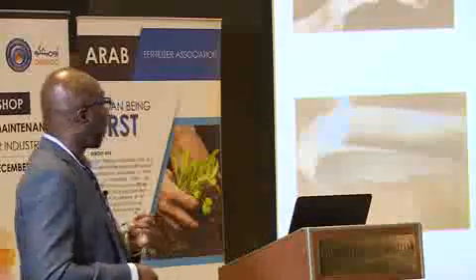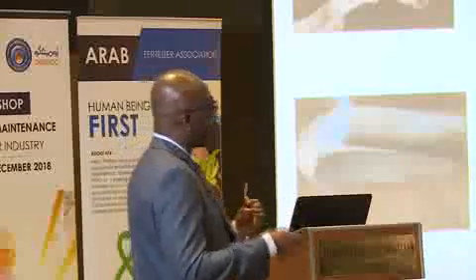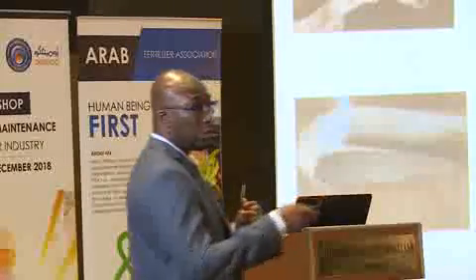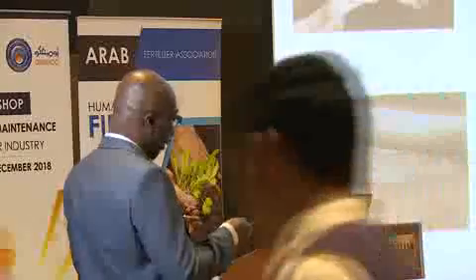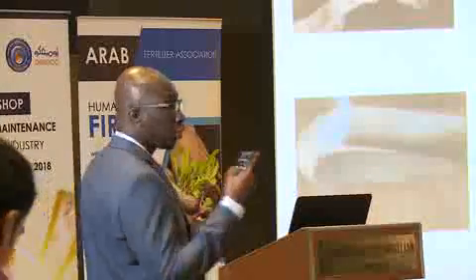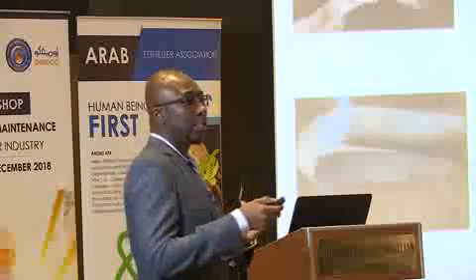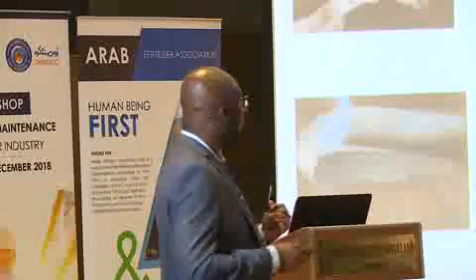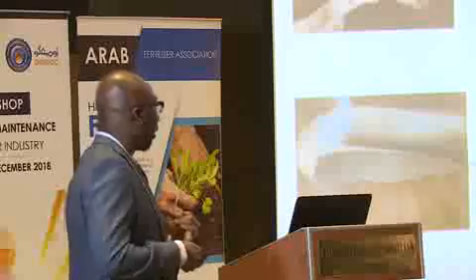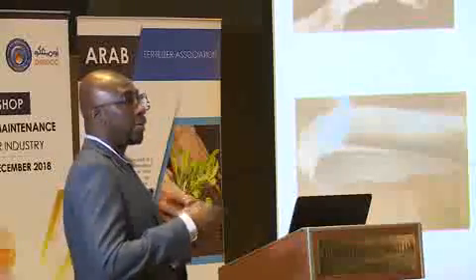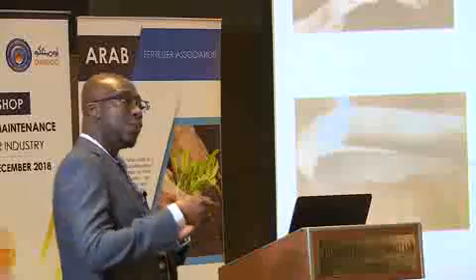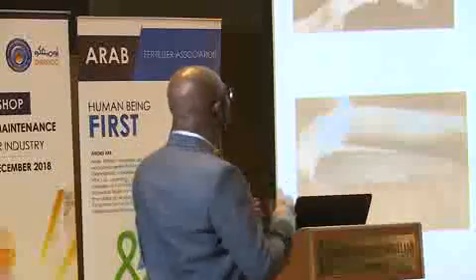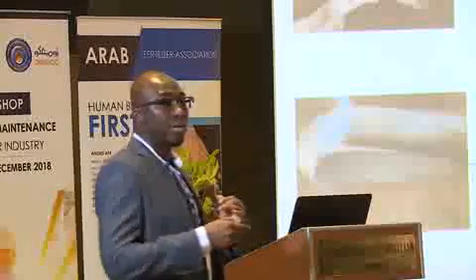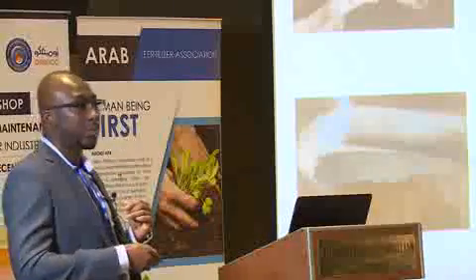When we introduced Safurex, we realized that just by changing our material of construction, we've eliminated all these corrosion issues. And when it comes to the cross-cut end attack, there are two issues. When you have Safurex tubes, yes, at the cross-cut face there is some slight attack, but it is not a life-determining factor of your vessel. But also, we had certain equipment made in Safurex which have cross-cut faces which had some issues, and we solved that issue by having another development in Safurex, which I will talk about towards the end of this presentation.